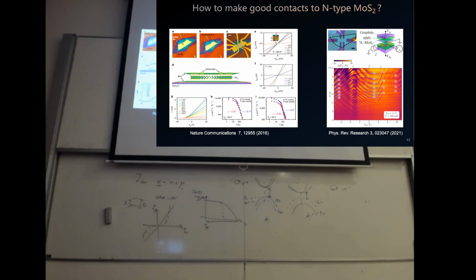And people didn't really use bismuth or antimony. We don't know why, but there are some other methods. One such method is you just etch the top hBN partially, so that you stop right at the surface of MoS2 or other TMD materials. Using this kind of surface modification or bonding between the metallic contact and the material, this problem can be solved partially. You can really get a high mobility up to 20,000. You have IV curves very linear at 2 Kelvin and see the quantum Hall effect.